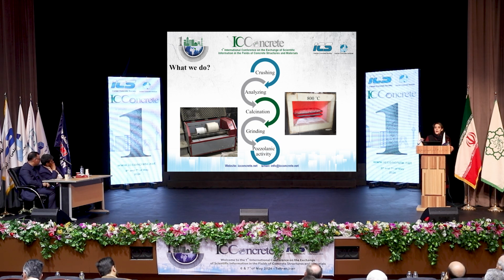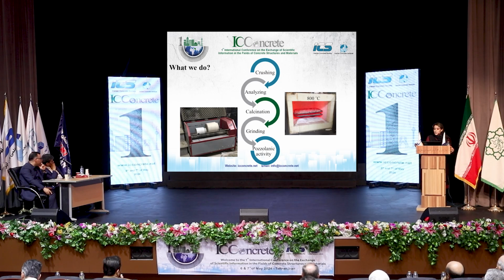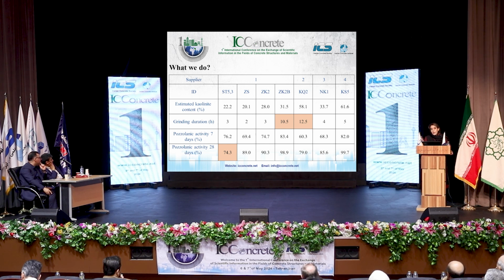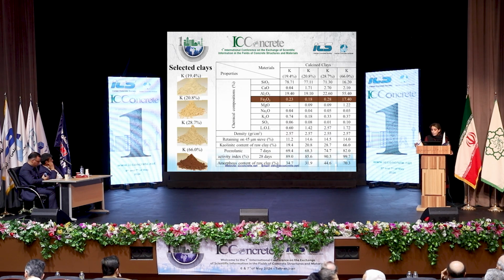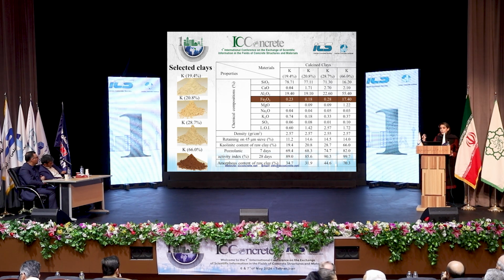First we crush and then analyze the raw clays, and after that we calcine the clays in a laboratory furnace at 800 degrees C. After that we grind the clays, and finally we measure the pozzolanic activity. We have 7 different samples of raw clays. 3 of them were rejected because of the duration of grinding time, and also the pozzolanic activity was not very proper. We selected 4 different clays with different kaolin content in their structures. As you can see in the picture, the different content of iron oxide results in different color in the clays. And increasing kaolin content results in increased pozzolanic activity.